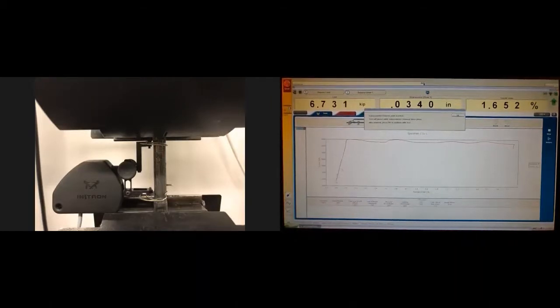So in general, what you can see here is this first linear portion of the curve right now, starting somewhere at the 0 mark for the strain. And since we have some pre-straining of the specimen, we see this little gap between maybe 1,000 and 1,500 pounds, and this is because of pre-straining. And then we loaded the sample up until some yield limit, and it should be calculated using a tensile strain of 0.2%. As you can see, it is in percentage right now.